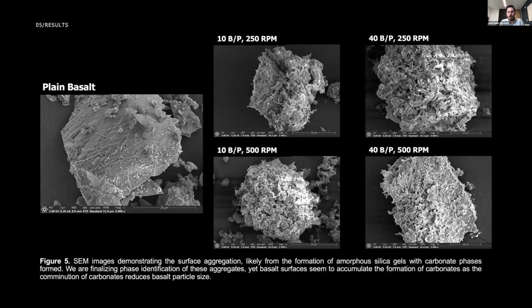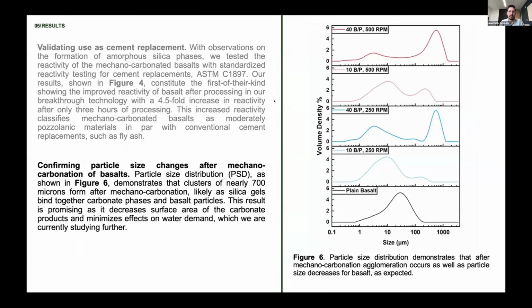Because we were really interested in this cluster formation, we wanted to run particle size analysis of the mechanocarbonated basalt. For 40 ball to powder ratio, we see really large agglomerates forming near 1,000 microns. This is fascinating because a big concern that we have in the cement and concrete field is that if we are milling, we are going to increase water demand for these cement replacements. So one key thing here is controlling the amount of surface area that we're generating through milling, and this agglomeration and clustering may be beneficial for controlling that water demand. Now, we're looking at those investigations further to tease out how workability and water demand can be affected.